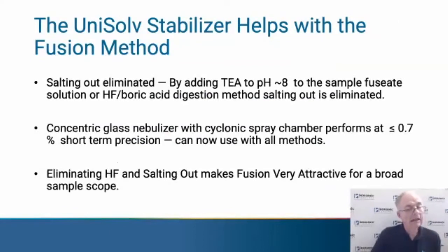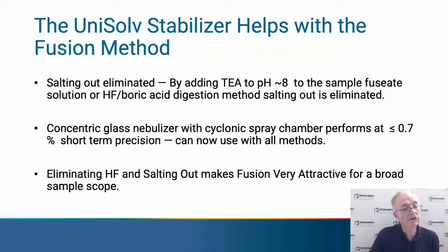Now, it helps either the fusion or our regular acid digestion, and that's the stabilizer we talk about, bringing the pH up to 8, rendering the HF non-toxic to your skin, because you get rid of the HF molecule. And so you basically eliminate salting out effects and the drift that occurs when you have an acid solution of boric acid.